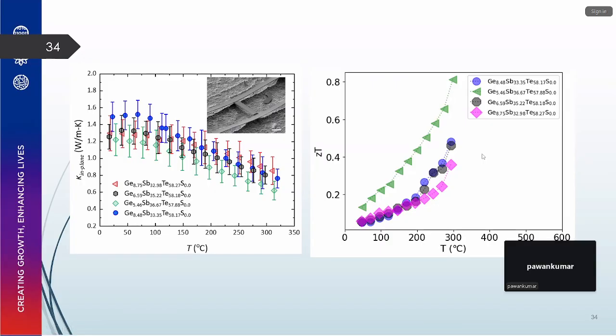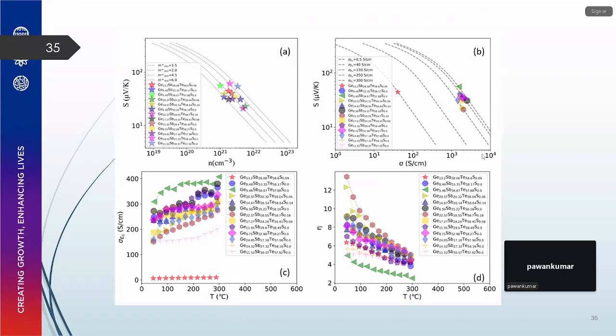Then we did some analysis of why we have this enhancement in the properties. We plotted the Pisarenko plot first. We measured the Hall measurement of the samples at room temperature. We see that the sample which gives you the highest ZT has the highest effective mass. Somehow this antimony is improving the effective mass of the system, which has also been reported in the literature. We also did the Jonker plot to see whether the sigma-zero is improved, which is also observed.